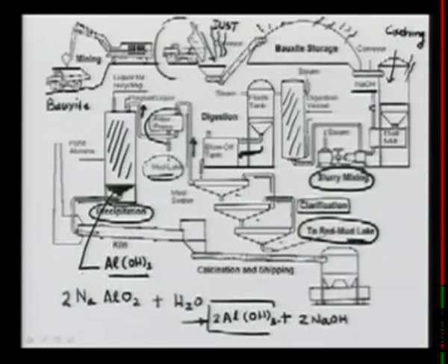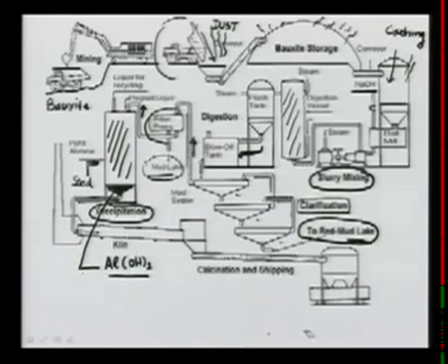Okay, let's see then where do we go from here. Sometimes we also need to, because this solution of sodium aluminate is supersaturated, we put some seed here. Seed that will help in the precipitation. So what you say here, the ppt of alumina, or some seed is also added. So seed is nothing but again from the Al2O3.